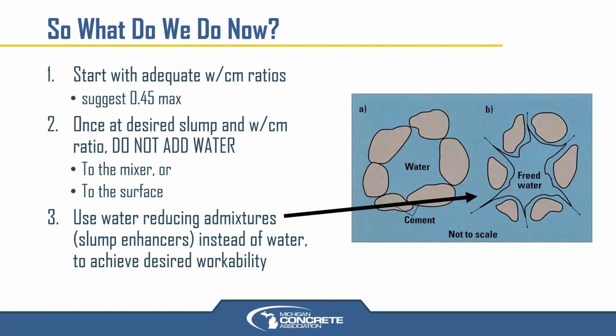Don't add water to the surface. I see that as well, finishers doing that. They want to close it up. They want a good looking surface. And water is not necessarily your friend if you need that all the time to aid in finishing. Elevating the water cement ratio reduces the strength and increases the porosity, and there's a higher chance of that surface having issues in the future.